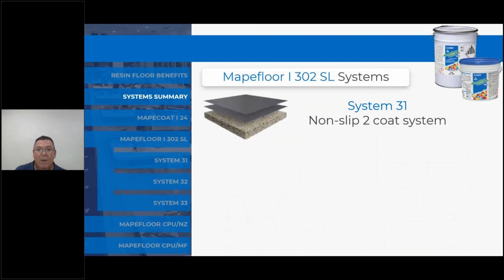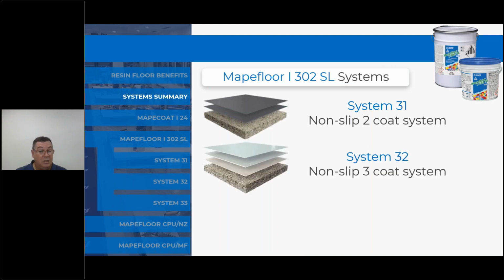Okay, so we start to talk about some of the systems in the Mapefloor I-302. The system 31 is a non-slip two-coat system, so that's the application of a primer and a top coat. The system 32 is a broadcast system, so it's also non-slip. So it's a prime coat and a base coat, broadcast, and then top coat to seal.